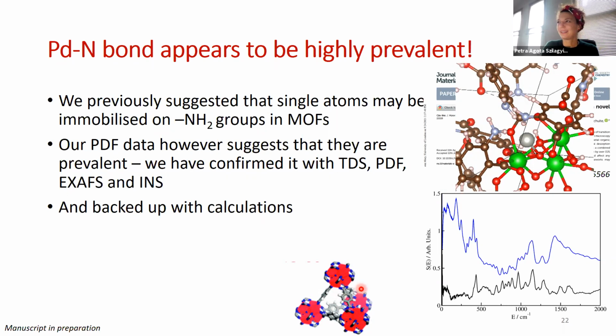But then I think in that case, we wouldn't see much difference in the inelastic neutron scattering data, because for that very reason, because they interact, the rotation would already be hindered. So in that case, probably not, but it is very possible that if you have larger groups, then it wouldn't be possible for them to surround the corner, or potentially that would already yield some kind of blocking of the rotation.